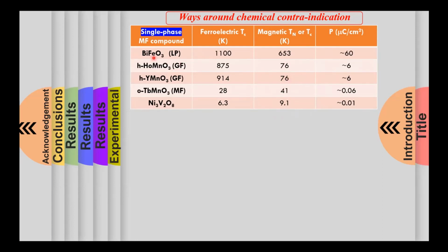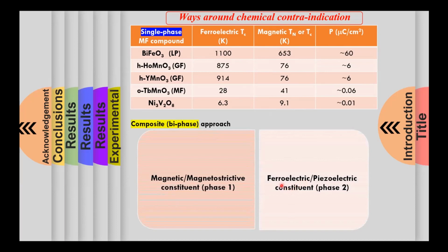BFO, the bismuth ferrite compound, is basically the only single-phase room temperature multiferroic, since its magnetic transition temperature and the ferroelectric Curie temperature are well above room temperature. The other approach to overcome this chemical contraindication is engineering two-phase multiferroic composites, that is, combining a magnetostrictive or a magnetic phase with a ferroelectric or a piezoelectric constituent.